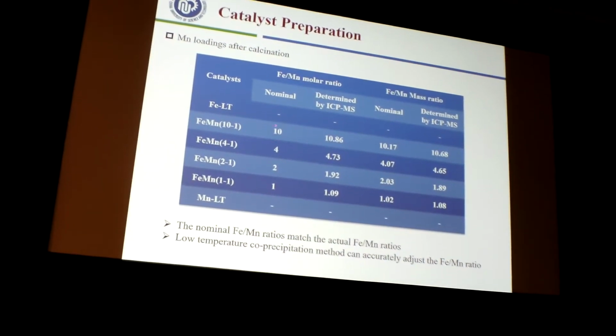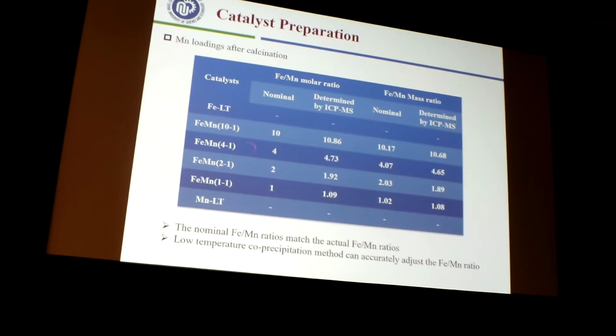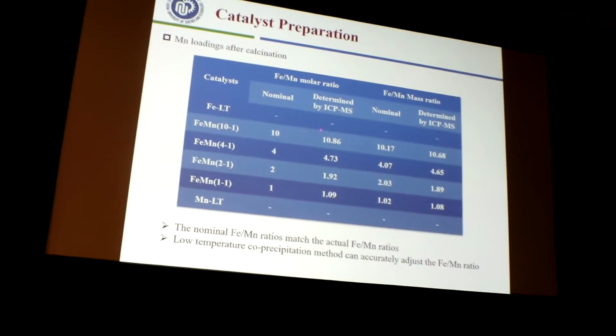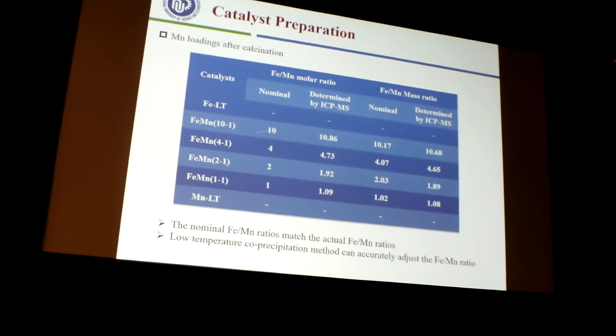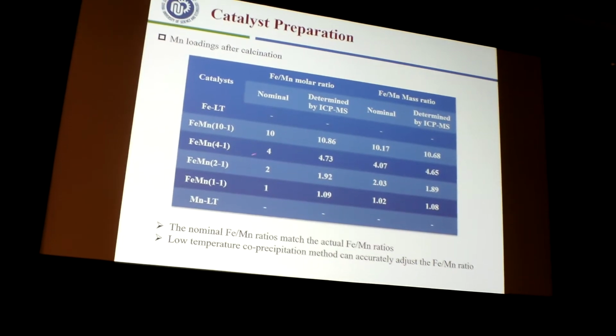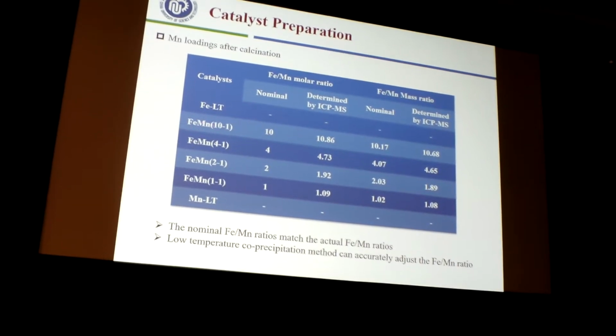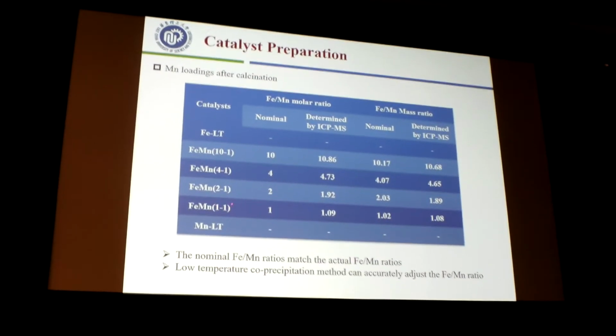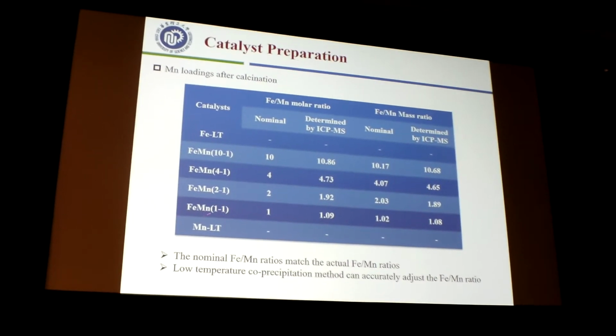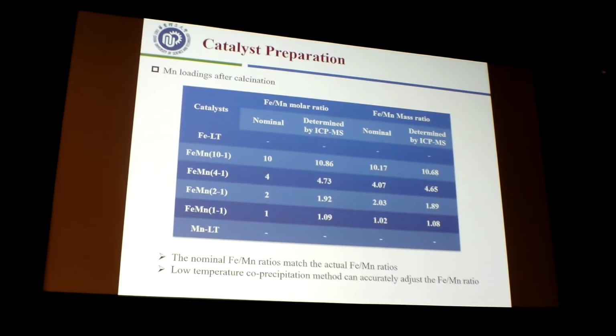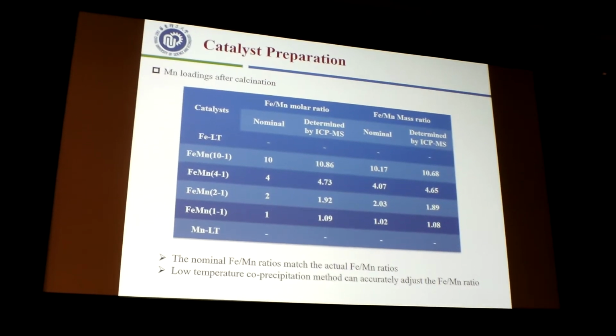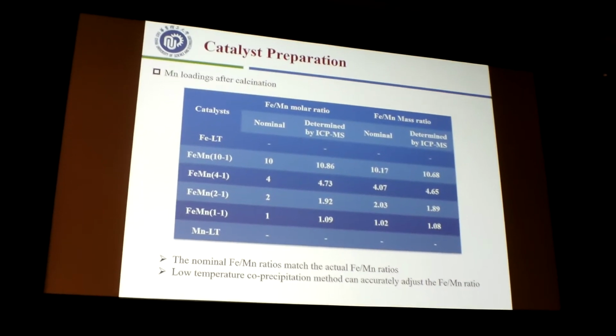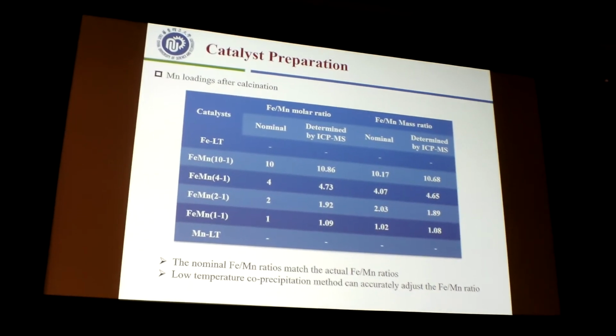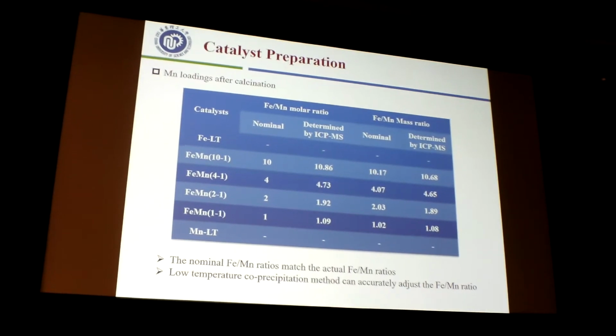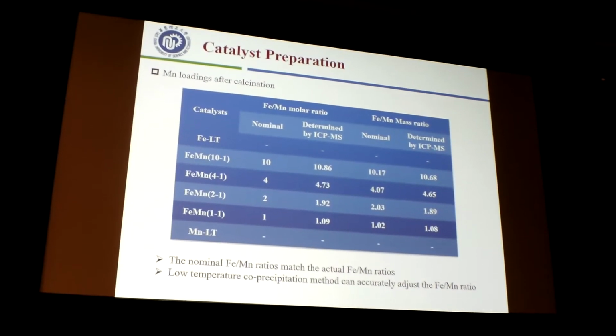After we calcine our catalyst, we measure the metal content in the catalyst. In this series of studies, we changed the manganese loading, with the iron to manganese ratio ranging from 10 to 1, 4 to 1, 2 to 1 and 1 to 1. We can see on this table that the nominal iron to manganese ratios match very well with the actual iron to manganese ratios, which means that the low temperature co-precipitation method can adjust the iron to manganese ratio.